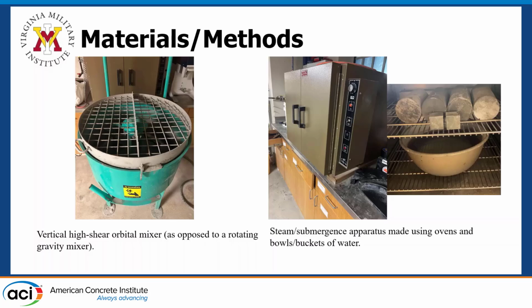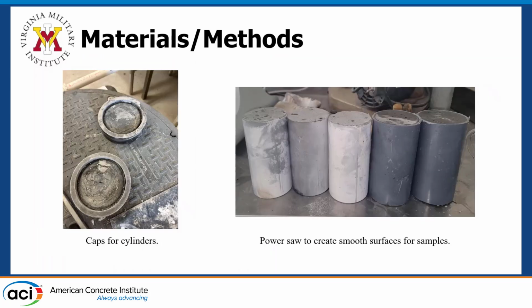We used a steam/submergence apparatus made using ovens and bowls and buckets of water. So every single day I would go down to the concrete lab and refill buckets of water in order to facilitate making a proper steam apparatus. Going on, we have the caps for our cylinders. We ended up using 3x6 cylinders as opposed to 4x8s. The reason being, based on the orbital mixer, we didn't have a high amount of volume that we could work with, so we tried to cast as many samples as possible.